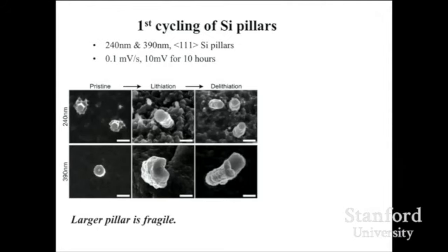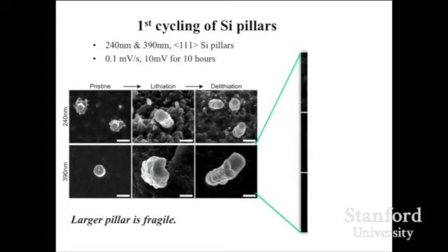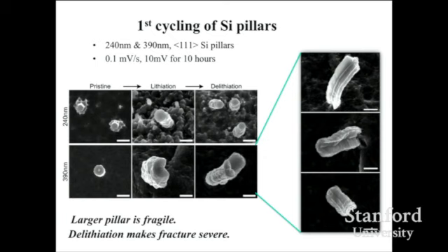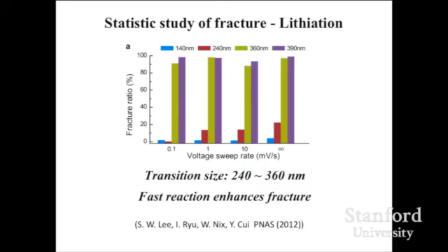And now let's look at the breaking, right? Our intuition tells us that if the structure is small, it doesn't break anymore. So how big is too big, such that they will break? We patterned different sizes of pillars, 240 and 390. You see 390 breaks right here, but 240 does not. So this, for example, is a picture of breaking right there. Pretty much we figured out that 300 nanometers is the critical size. Below that, it doesn't break that often. Above that, they break very often.